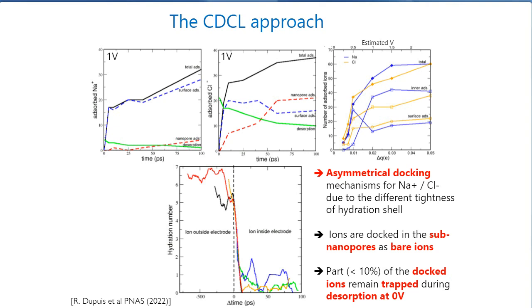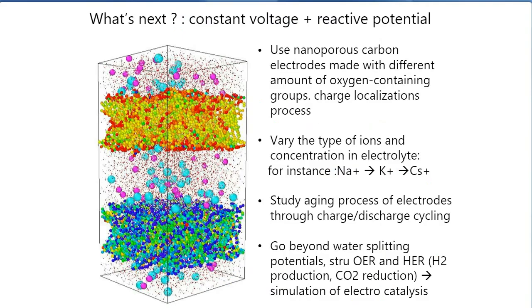We did three cycles — all of this with a rigid electrode where carbon atoms cannot move. This 10% of trapped ions is a constant — they are contributing to capacitance but cannot get out, meaning they are lost in terms of participating to the supercapacitor device. So that's really the mechanism: a symmetrical supercapacitor but a very asymmetrical behavior of the electrodes. This asymmetrical behavior was also measured experimentally, not in the case of an aqueous electrolyte but for ionic liquid systems.